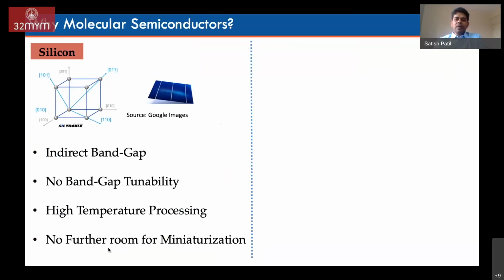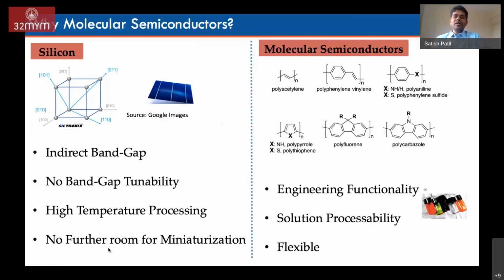If you compare, molecular semiconductors are a distinct class of materials, with several advantages over silicon. In molecular semiconductors, you can engineer the functionality and tune the band gap. For example, with the chemical structures shown on my slide, you can tune the band gap from almost 3 eV to very low band gap semiconductors below 1 eV. And you can also improve the solution processability.